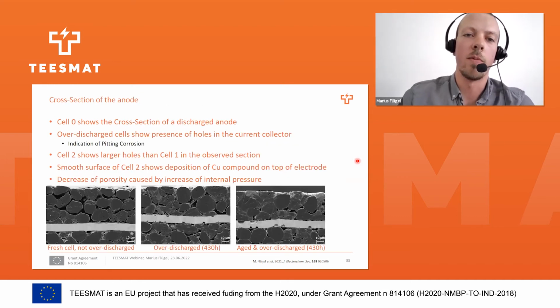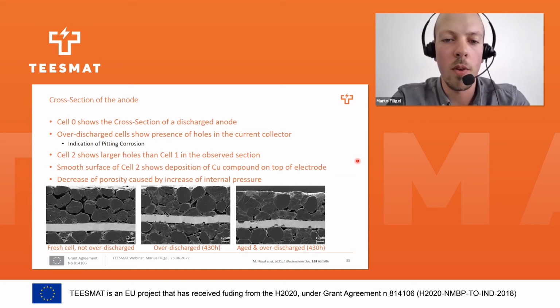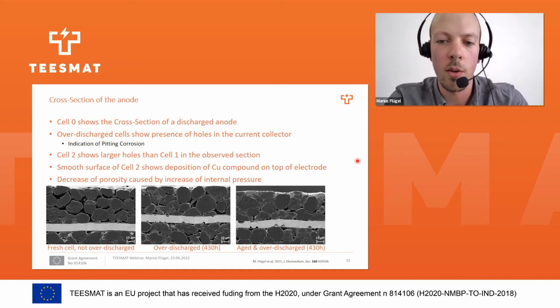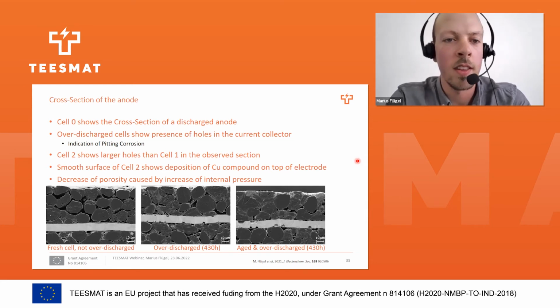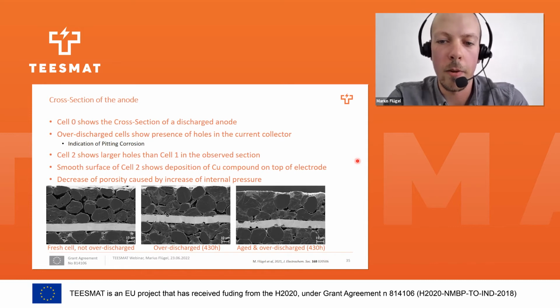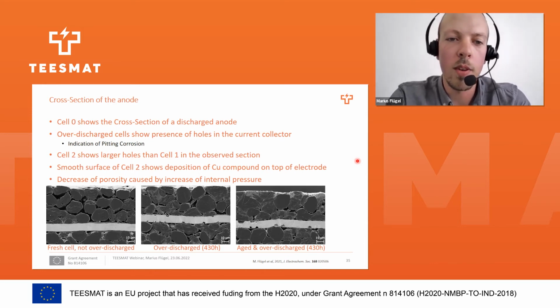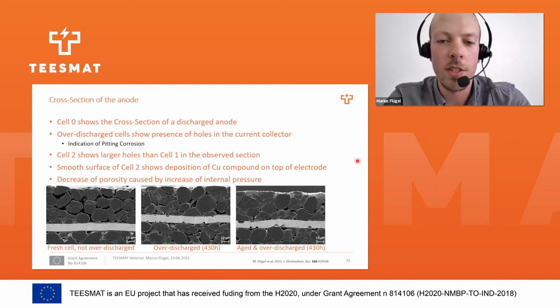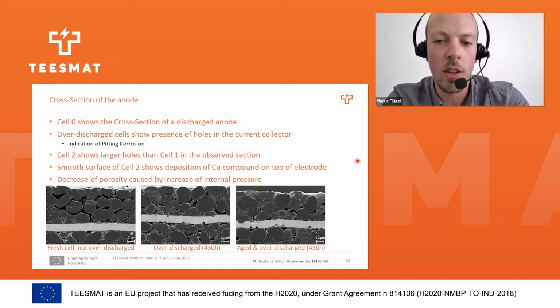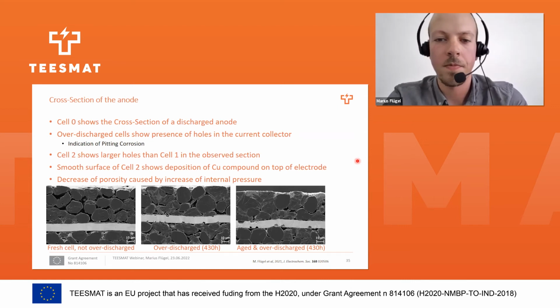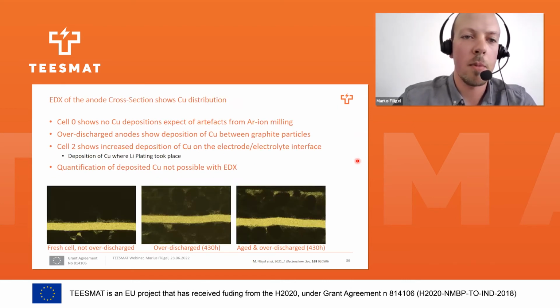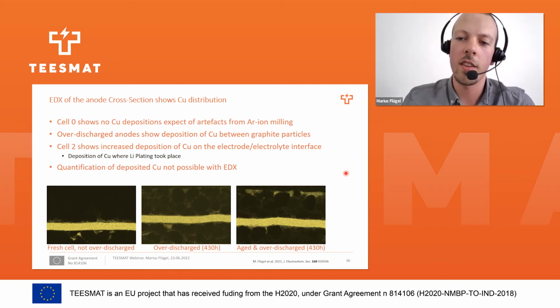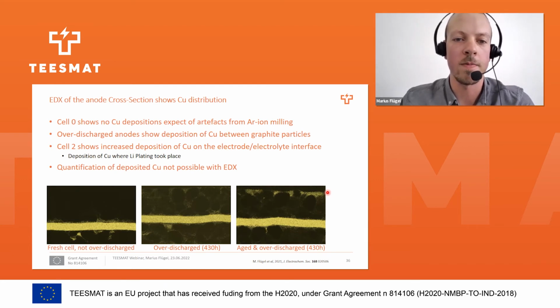The cross-section of those cells revealed that the copper originated from the copper current collector, obviously, and the copper current collector showed signs of pitting corrosion instead of homogeneously dissolving. And the holes of the current collector of the previously aged cell were much larger, which is in agreement with the ICP results. EDX mappings of those cross sections showed that the main amount of copper is redepositing at the anode surface.